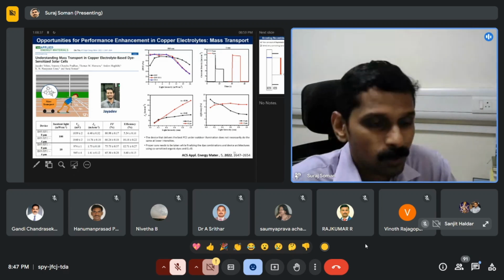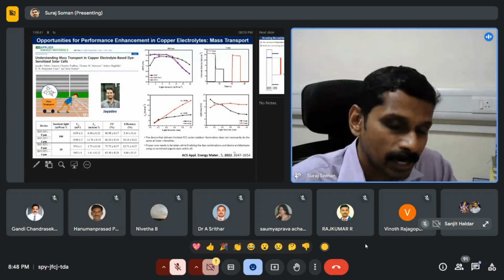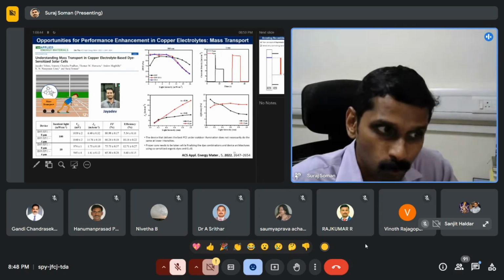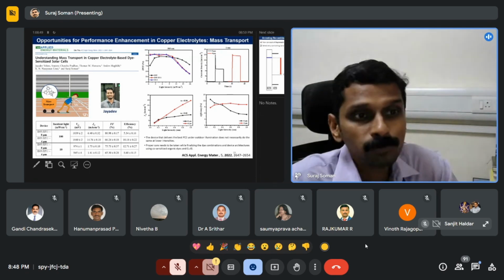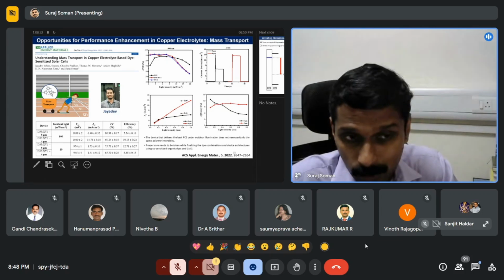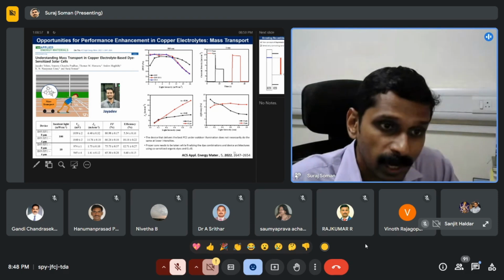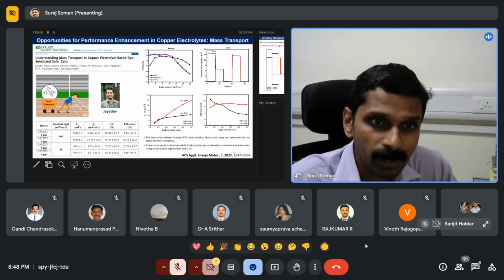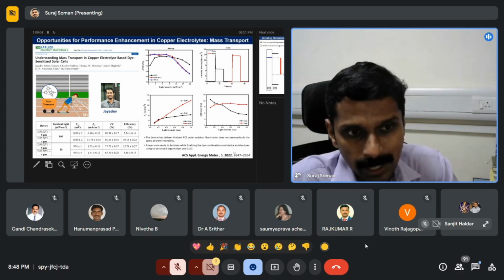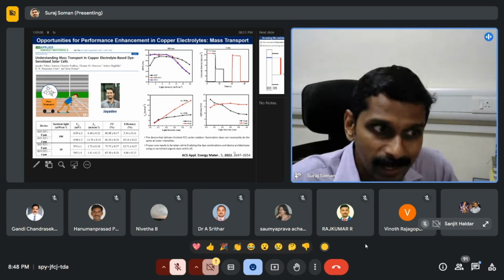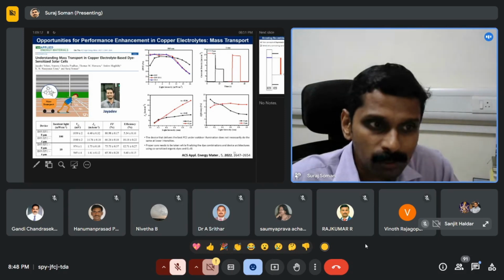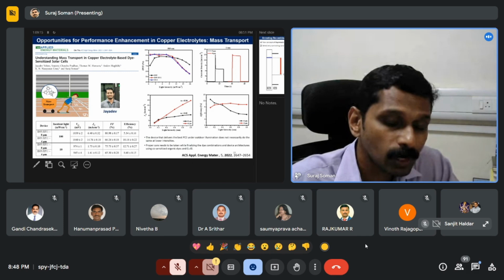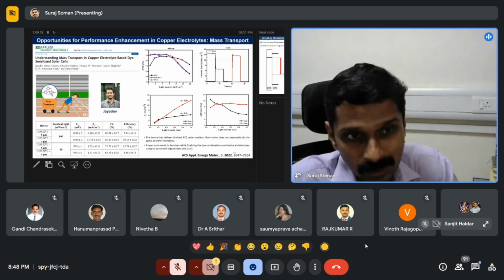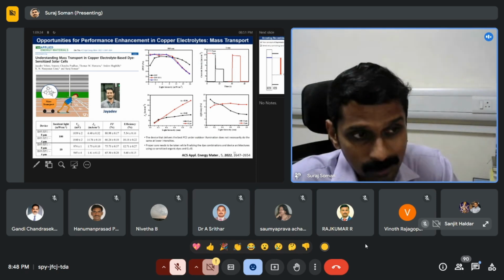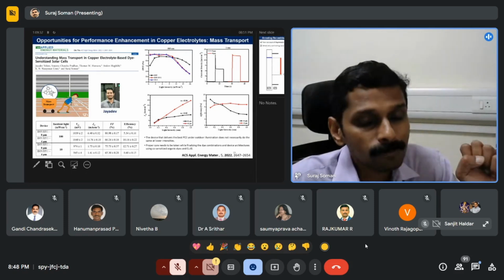So what is the take-home message here? When you go for a lower intensity condition, the device architecture and the thickness of the TiO2 that you need is totally different from what you use for one sun. This is a major piece of information that came out of this paper, because it is a general rule of thumb that people make devices for one sun condition and take the same devices for indoor measurement, which is not right, because the light spectrum for one sun and for indoor are totally different. So you need to completely rework the devices. You need to innovate on the architecture, on the porosity of the semiconductor, and design molecules custom for indoor photovoltaic applications. This was a very unique result that we put out.